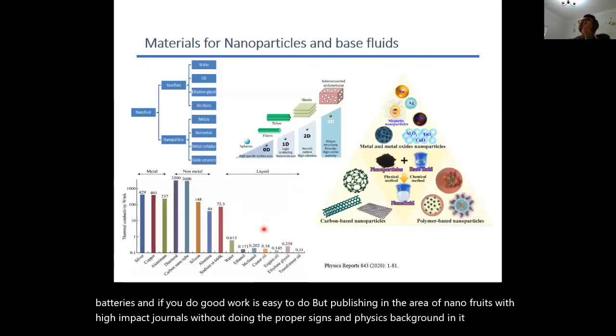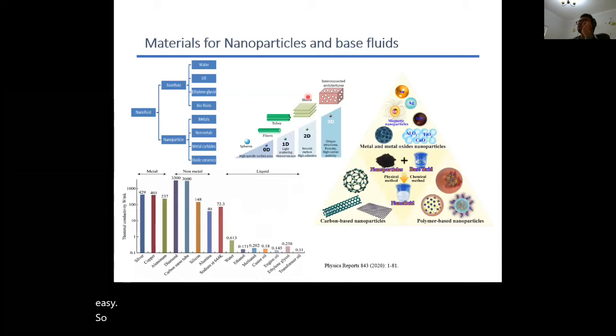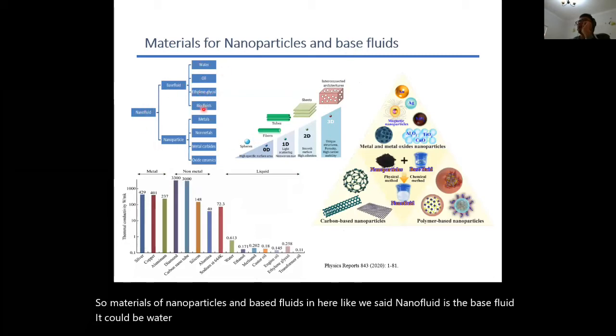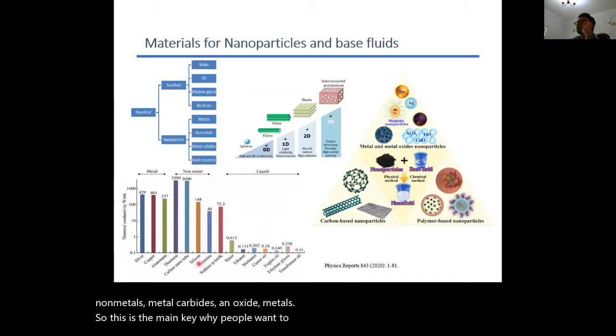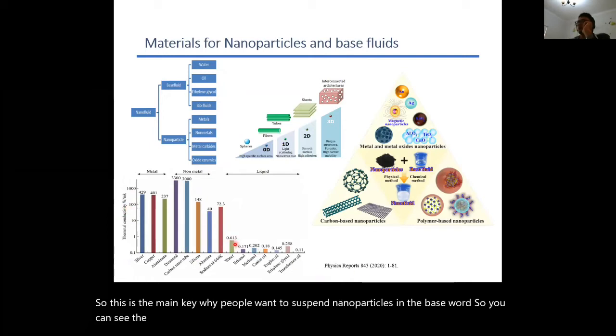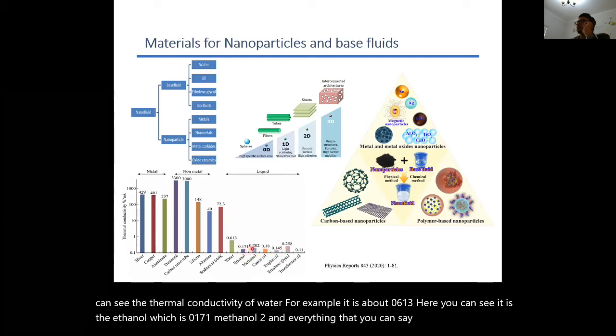So for the materials of nanoparticles and base fluids, like we said, nanofluid is the base fluid. It could be water, oil, ethylene glycol, or bio-fluids. The nanoparticle could be metals, non-metals, metal carbides, and metal oxides. This is the main key why people want to suspend nanoparticles in the base fluid. You can see the thermal conductivity of water, for example, is about 0.613. Here you can see ethanol, which is 0.171. Methanol is 0.2, and everything else is below 0.2 and onwards.